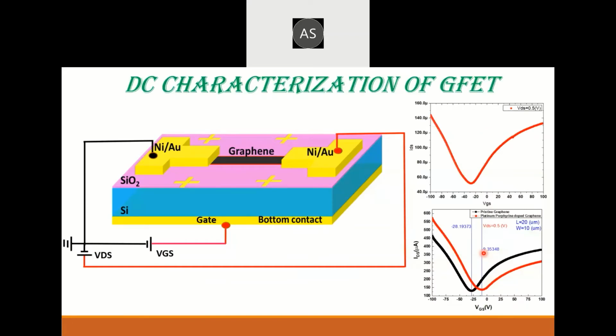And the experiments that we did after optimization of the sputter: we made backgated graphene field effect devices. The idea behind making these GFET devices was to see how electrically active these dopants are on your graphene. We simply made source drain contacts and a graphene channel, and we were interested in doping this graphene channel with our porphyrin with different polarities. We found that if we dope this graphene channel, then the Dirac point can be shifted. So your charge neutral point, or Dirac point, is shifting with respect to gate voltage.